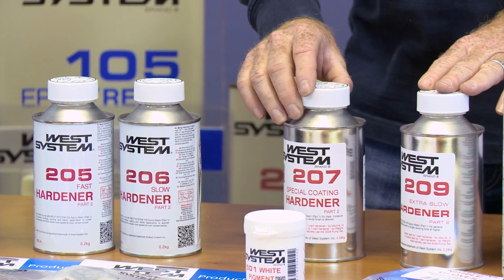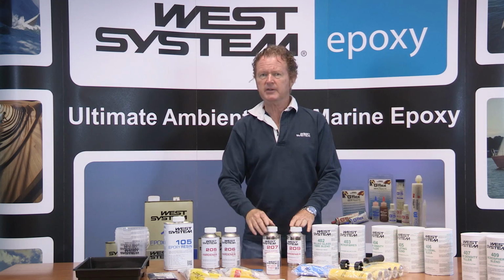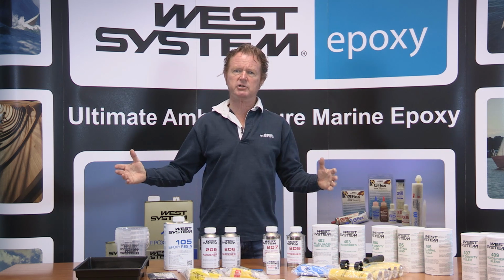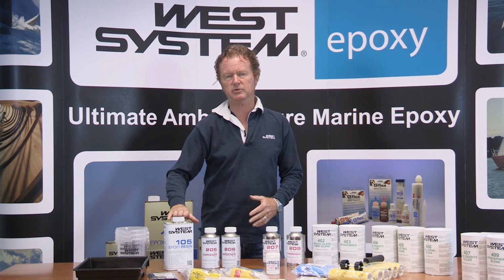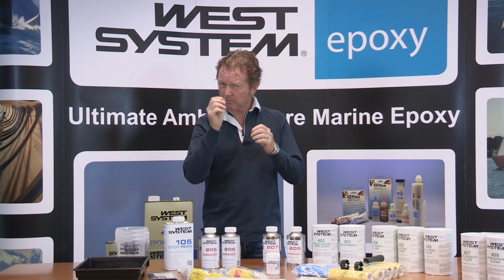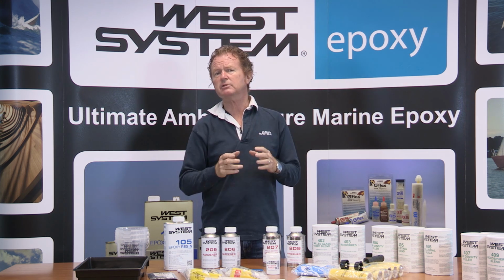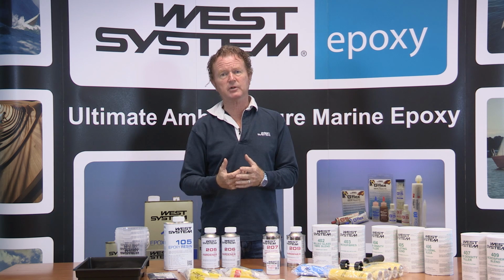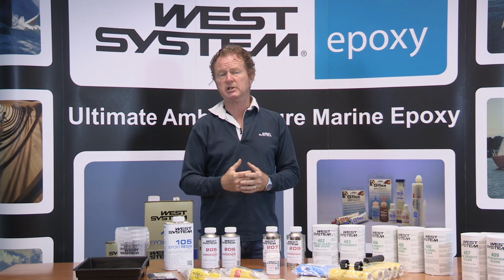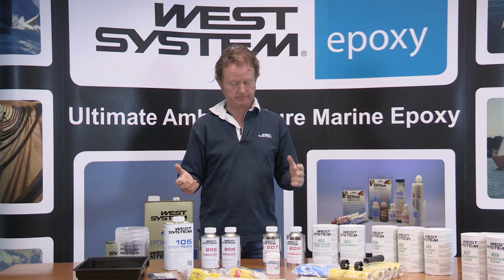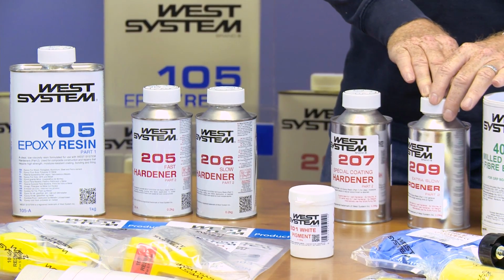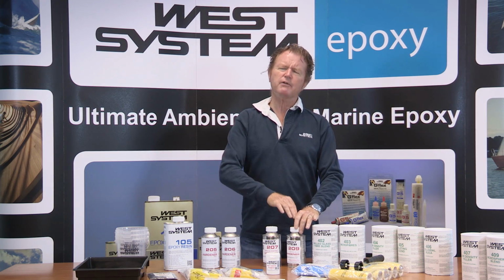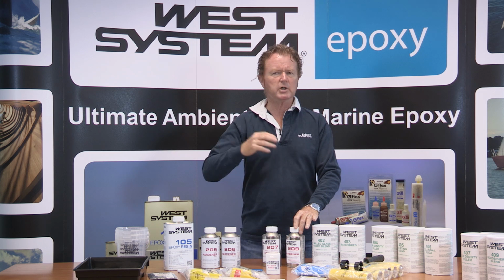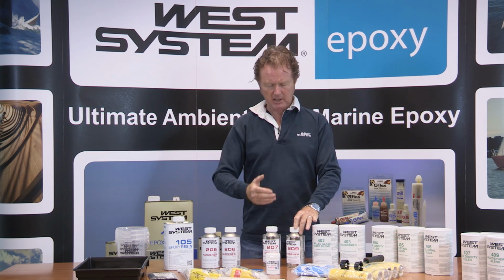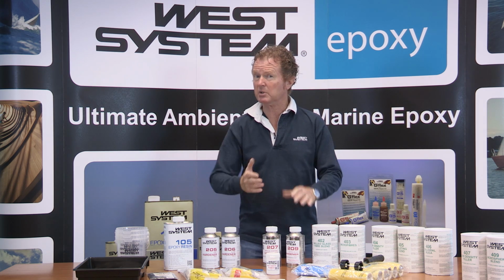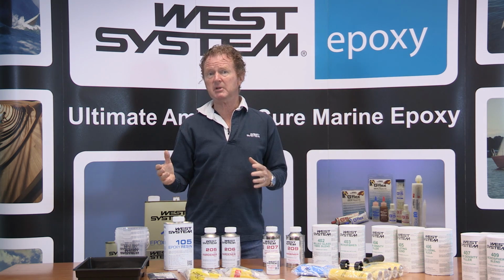Our 207 is a special coating hardener. This gives you fantastic flow characteristics when mixed with the 105 resin. And it has some, but only a small amount, of UV resistance. It must be overcoated with a very good quality two-component varnish system. Our 209 hardener is very, very versatile for very, very hot conditions where you're working above 18°C. This will give you a pot life of somewhere between 50 and 70 minutes.